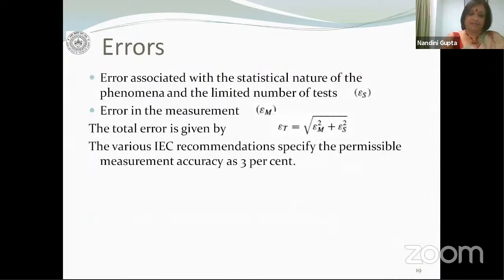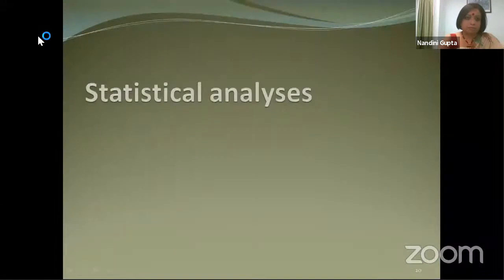Aging tests are, of course, like any other test, associated with a certain number of errors. And most of these errors come because of the statistical nature of the phenomena, number one. And secondly, no matter how large your population sample size is, it will be limited by very many other factors other than statistics. And therefore, you will always be performing a limited number of tests, and that will result in errors. So the total error can be roughly estimated as a combination of the measurement error. Any diagnostic test will have some measurement error, combination of the measurement error and the statistical error. And various IEC recommendations specify the permissible measurement accuracy as 3%.